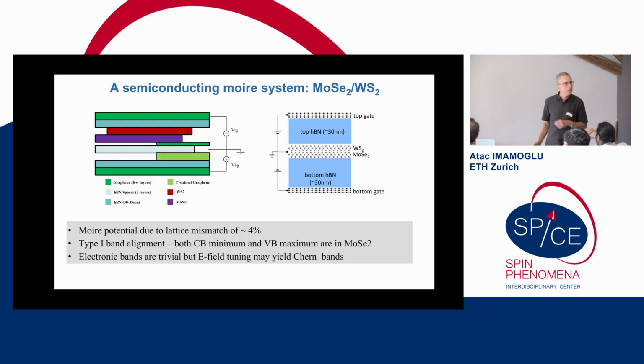So we want to put this into work. We consider a moire system. In this case, it's not twisted, at least we did not intend it to be twisted. These two materials with different chalcogens have a lattice mismatch of 4%, which results in a moire period of about 8 nanometers. What is nice in this system is that it has type 1 alignment,